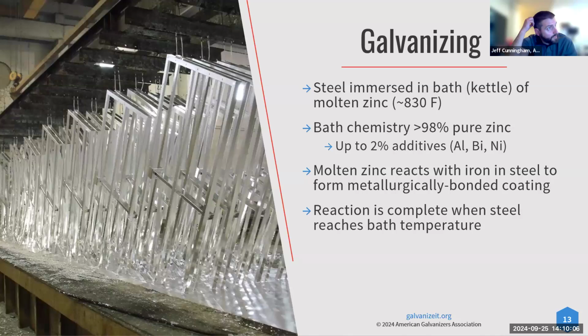All right, next comes the actual galvanizing process. So the steel is fully immersed in the bath of molten zinc, typically around 830 to 850 degrees Fahrenheit. Bath chemistry has to be 98% pure zinc according to ASTM standards. Now, every single galvanizer I know is running at more like 99.5, 99.6. Up to 2% additives include aluminum, bismuth, and nickel. And mostly that has no effect on the coating. It's just the fluidity of the bath. It keeps it a little bit more fluid, so pieces have an easier time going in and out.